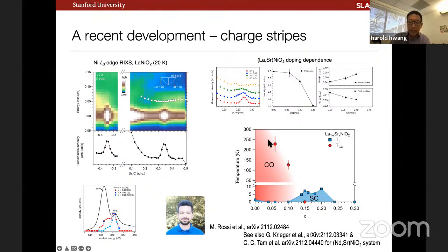There's approximately a 1/3 superlattice vector. And this is roughly, in the lanthanum case, how it looks: this intensity comes on and then comes down as we enter the superconducting dome. And I should say that just around the time that we put up our work on the arXiv, there were two other studies of the neodymium nickelate system that also showed these sorts of stripe features.